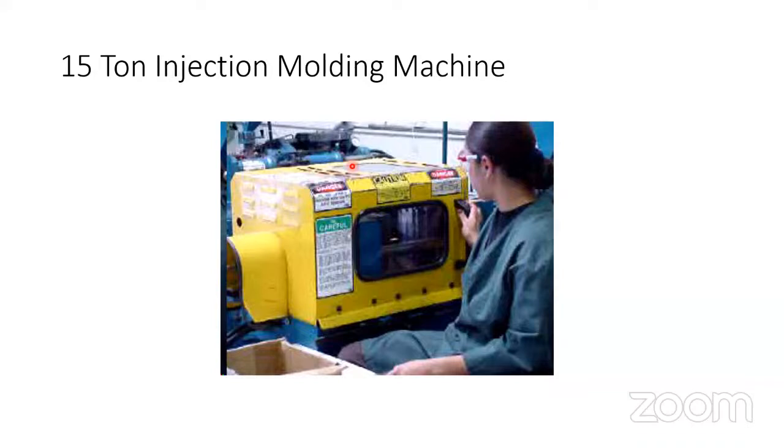Now see the thermoset material. We are heating the mold in the case of a thermoset, but in thermoplastic we are cooling the mold. This is a big difference. Therefore, such types of parameters differ.